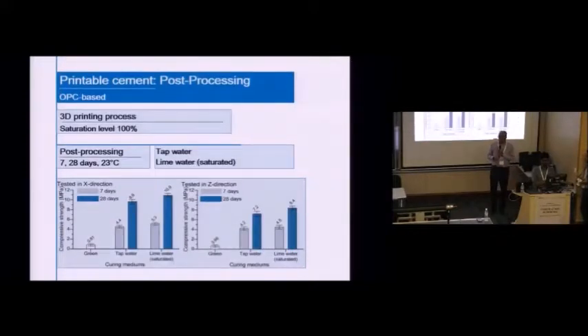This is post-processing using cement. So we used geopolymer, but we also used Portland cement. And then we cured the Portland cement in lime water. And we could get strength up to about 11 MPa, but we are working on increasing the strength beyond that for Portland cement.